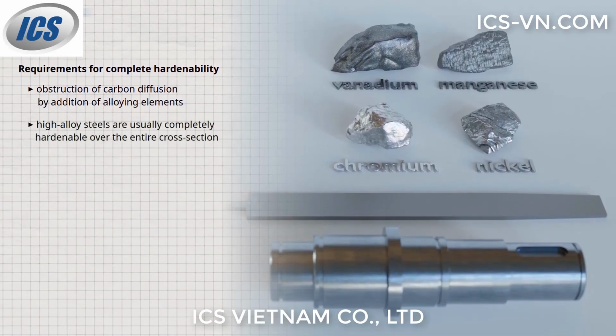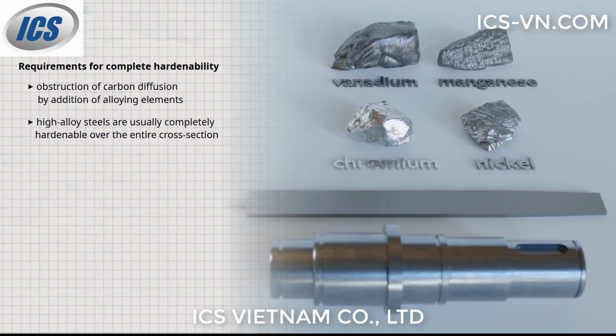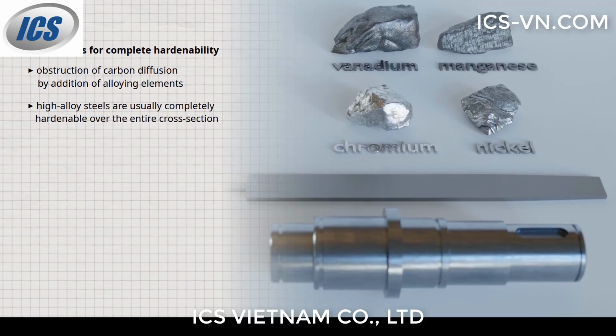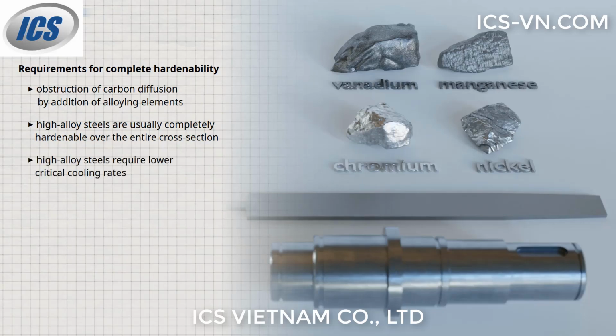As a result, high-alloy steels generally harden through the entire cross-section compared to unalloyed steels. High-alloy steels therefore require a lower critical cooling rate during quenching in order to form martensite.